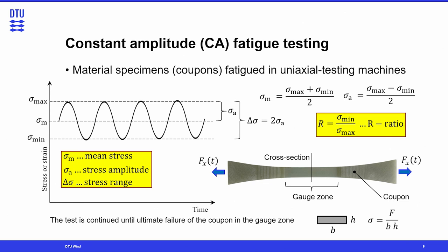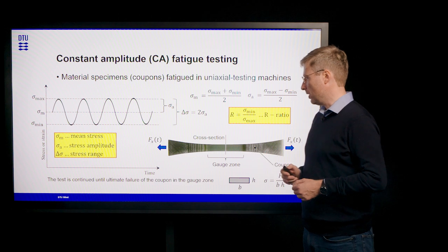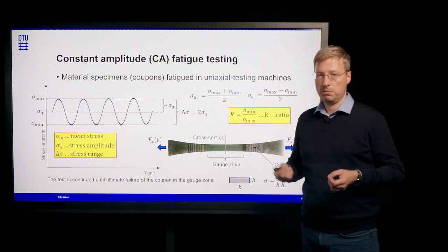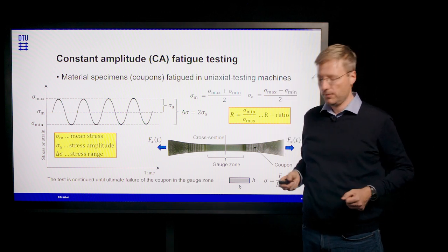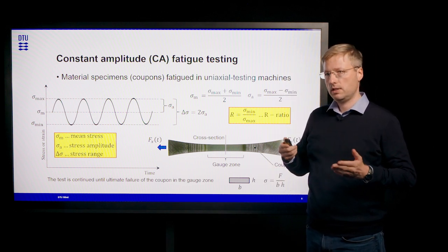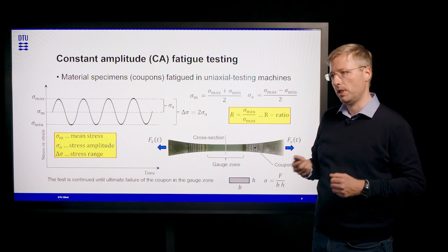How do we go about producing SN curves? It is a purely empirical process and the way we do it is through testing. The tests are done on so-called coupons. They have a special optimized shape — they look like a butterfly with a gauge zone in the middle. We take those specimens of a specific material and put them in a uniaxial testing machine, then subject them to a cyclic loading spectrum with a harmonic load signal.